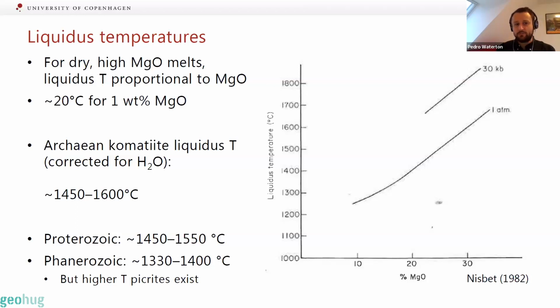For dry high magnesium melts, the liquidus temperature is proportional to the magnesium content. So basically for every 1 weight percent MgO you go up, the liquidus temperature increases by about 20 degrees. So when we apply this to Archean komatiites, and again, correcting for these small amounts of water, we get liquidus temperatures of between about 1450 and 1600 degrees C. For Proterozoic komatiites, although they're rarer, we get temperatures between 1450 and 1550. And Phanerozoic, this is just the Gorgona komatiites, we get temperatures between 1330 and 1400. It's important to note here that obviously this is just one locality, but there are higher temperature picrites in the Phanerozoic that don't necessarily class as komatiites.